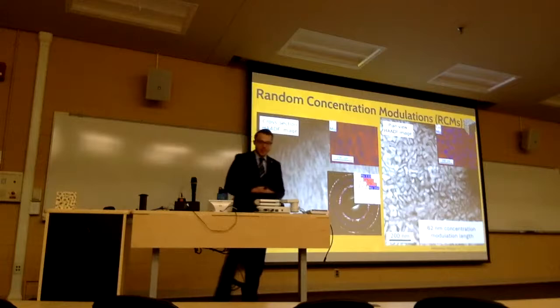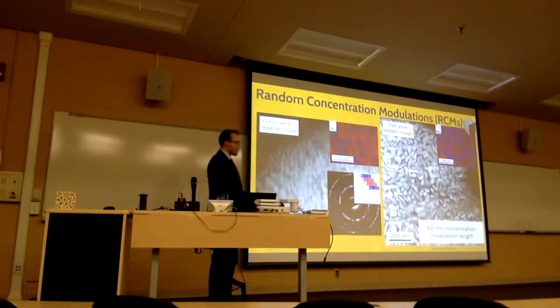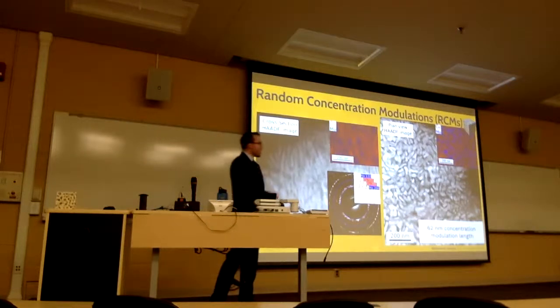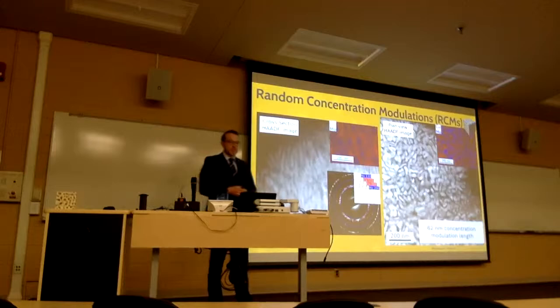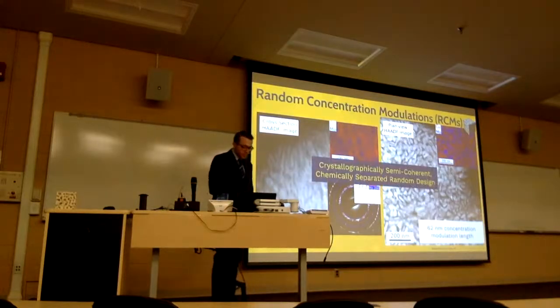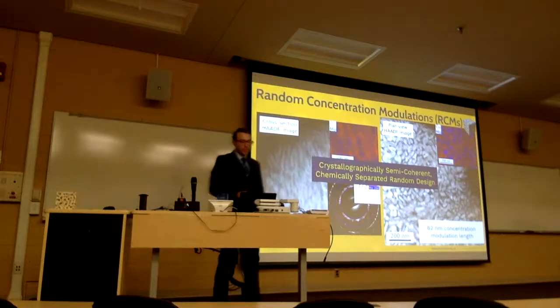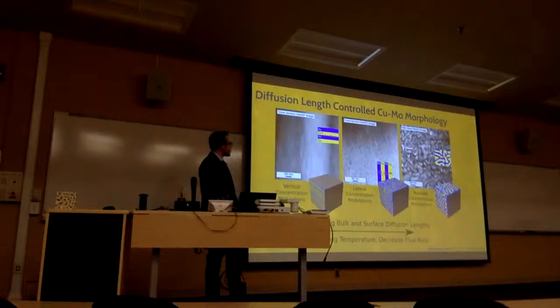At the high temperature, you can see where this is going. We actually have a randomization of those phases in both cross-section and in plan view. And we can see we have a much more random crystal grain orientation in the sample. We've lost some texture. We have a much more tortuous bicontinuous-like morphology in both of those views of the sample. So here we have a random design in the morphology. So in summary, here are those three morphologies.